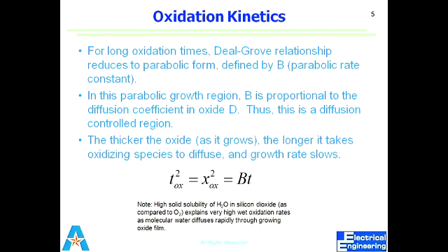I told you that previously it was not diffusion controlled, it was a reaction rate controlled region, because diffusion was not a problem. Now, because we have a thick layer, the problem is with the diffusing of those oxide molecules through the silicon dioxide. So the problem is with the diffusion. The diffusion is actually limiting our oxide rate. Oxidation rate is limited by the diffusion process, because whatever diffuses through would be reacted with silicon.